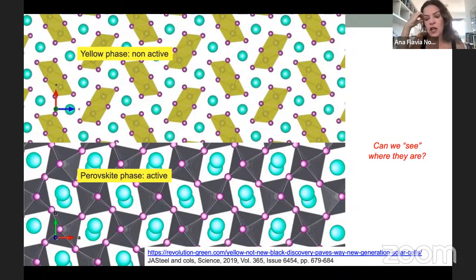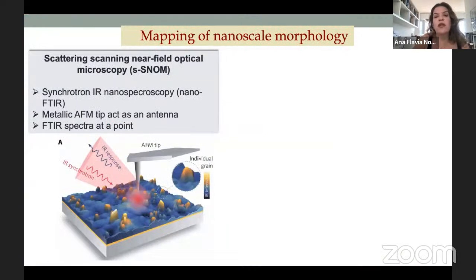Our first work in the synchrotron with metal halide perovskite was not with X-rays, but with infrared. So the question was, after forming the film, can we see where these yellow phases are in the film? This was the work of Rodrigo, the PhD of Rodrigo. He's now a postdoc in a synchrotron. So we used the infrared radiation from the synchrotron coupled to AFM.